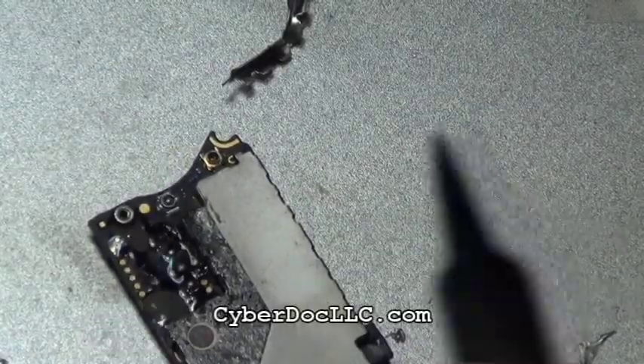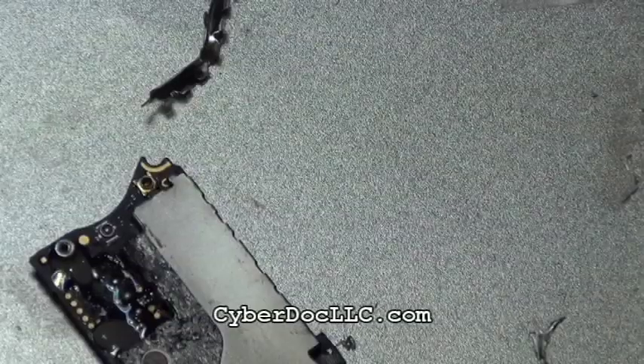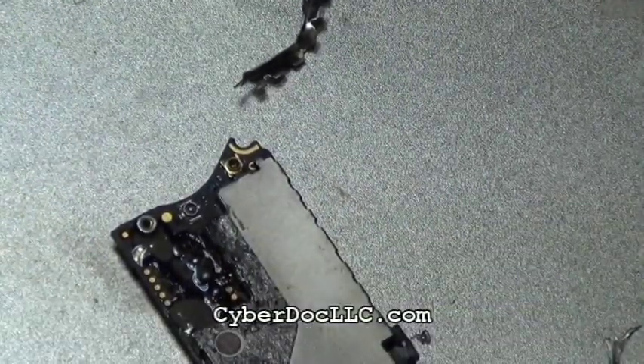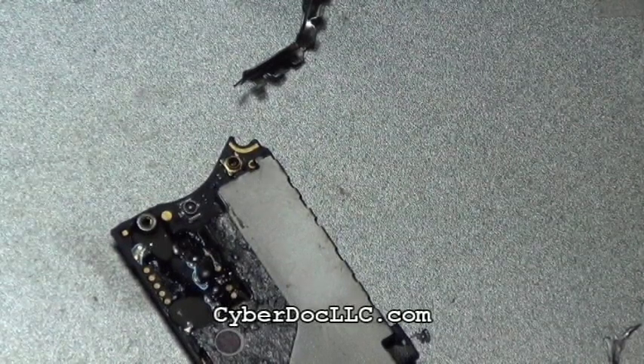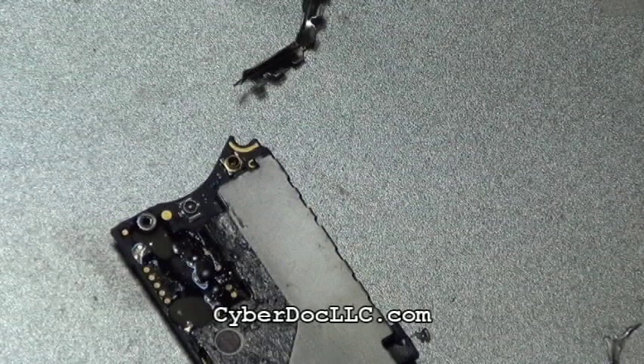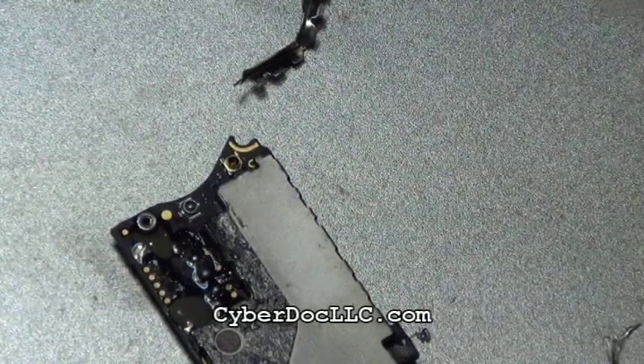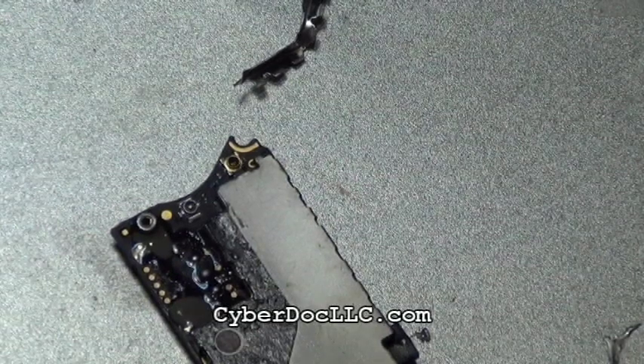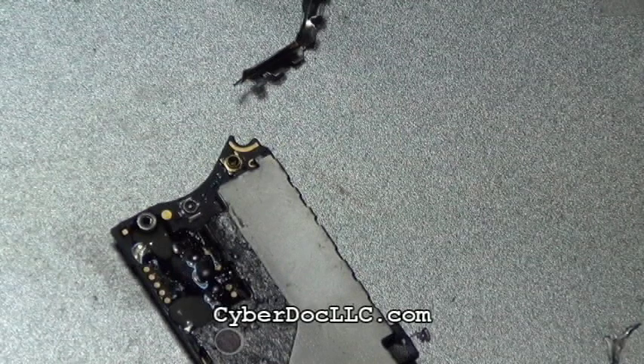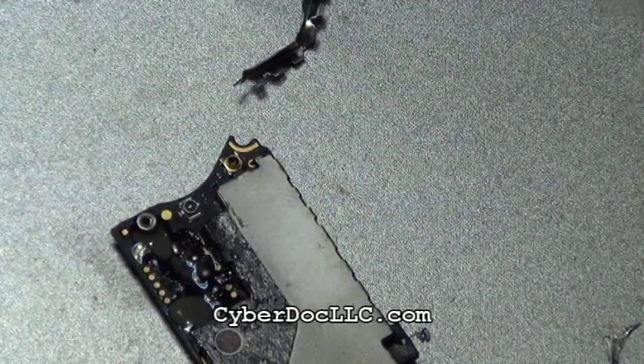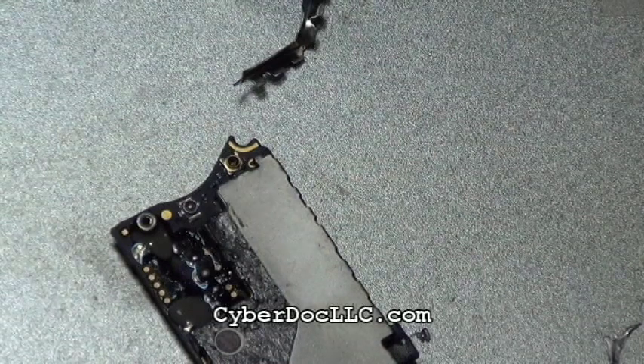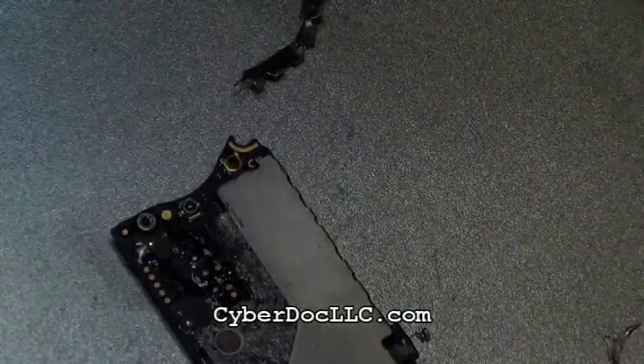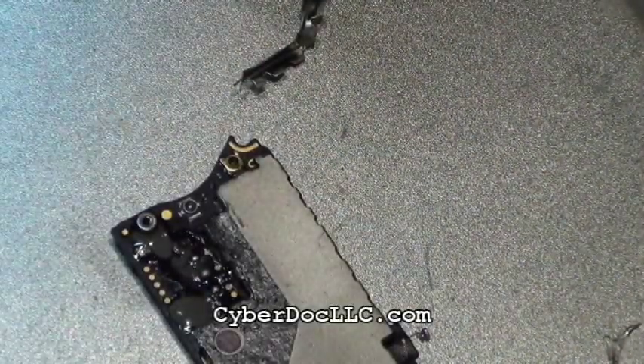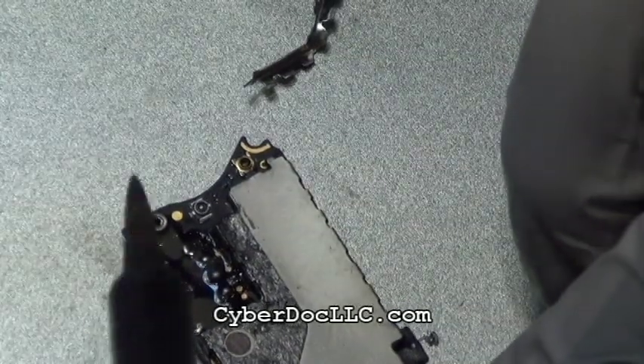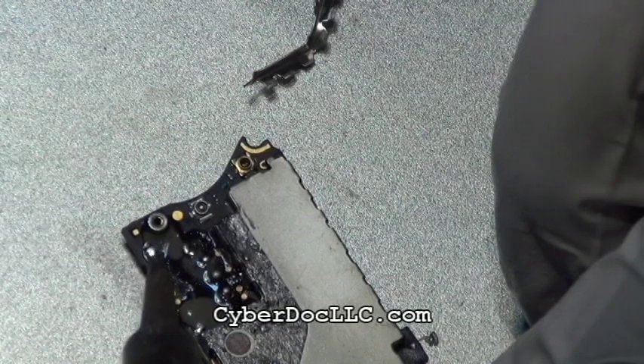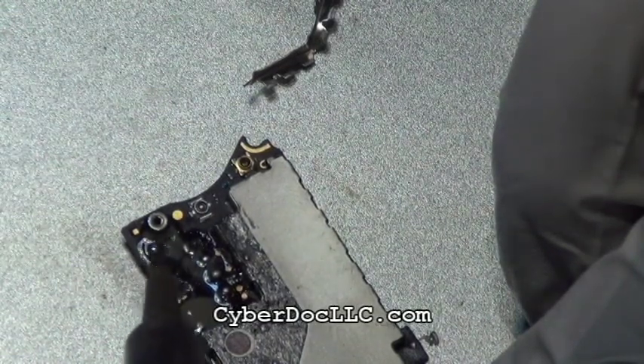First, you clean the board. You put some no-clean solder paste. I prefer the synthetic kind of solder paste, and the rosin-based or synthetic rosin-based no-clean solder paste, both of which you can find on our website, CyberDocLLC.com. The reason I prefer these is, first of all, they are no-clean solder paste. And second, the acid they use inside the solder flux is very mild. It's carboxylic acid, so it's not very aggressive to the logic board, it's not corrosive, it's not conductive obviously, and it's relatively no-clean.